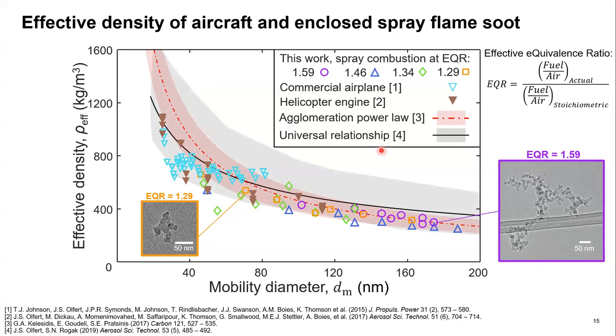The last thing we can look at is this universal relationship, where the authors of this study surveyed soot from many different sources, including aircraft, but also soot from different types of engines and different kinds of flames. What we see is that the line in the middle here is the average of all of these sources, and the shaded area is the bounds of the data that were surveyed. Our data and that of the commercial and helicopter engines are on the low end of the effective densities that are measured from this survey of the data. So what we can see here is that it could be that aircraft tend to produce soot with lower effective densities compared to soot from other sources.